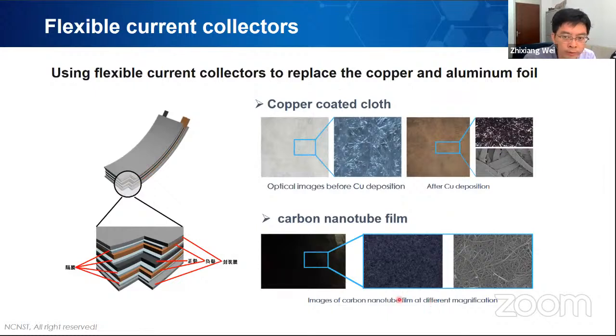For a real flexible lithium battery, not only the electrode material but the current collector is also important. For example, commercialized batteries use copper foil and aluminum foil as current collectors, but this kind of metal foil is not that flexible. We can replace the metal foil with a copper-coated cloth or a carbon nanotube film. They are highly flexible.